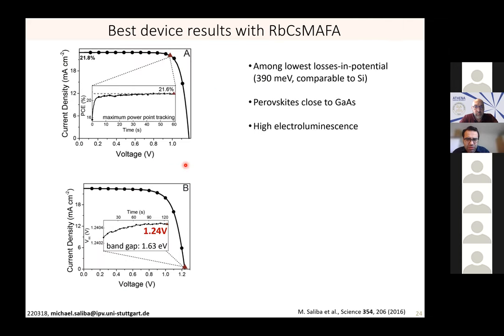And just here also to quickly talk about the results, by adding rubidium to the triple cation mixture, we could show that we achieved very high performances, but very importantly, the crystallization process improved such that a high voltage was achieved as well. And this is crucial for solar cells. A very high voltage is indicative of being relatively recombination free, I mean, a non-radiative recombination free material. And this is a metric for the quality of the material in general.